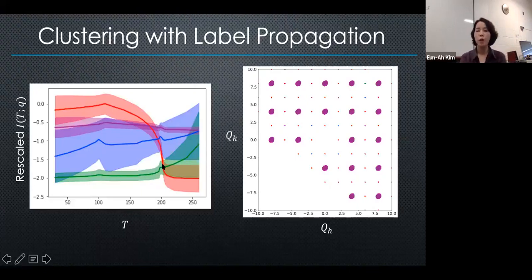This looks very simple, but this is the result of honest processing of 0.5 terabytes of data that only took about 15 minutes. And what's coming out when the whole process is done is these four different clusters. One of them, this red cluster, obviously has an order-parameter-looking dependence on temperature. And this approach is immediately interpretable because you see the spread and the mean, which is not something put in by hand, but is a property of the data itself.